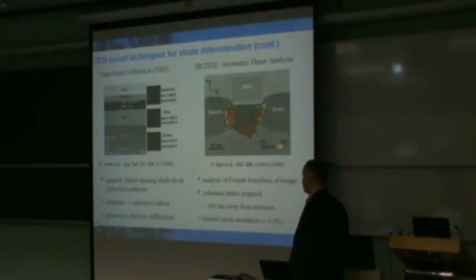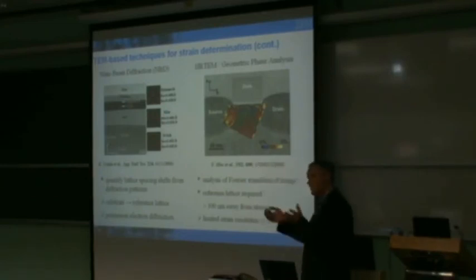So this is the analog of X-ray diffraction that I showed earlier, in which we're basically rastering the beam over a region of interest and using the silicon substrate as our reference to tell us what our unstrained values might be for the strain for the system. We then see that we're just simply measuring the change in the position of our diffraction points. And because, again, with electron diffraction, our Ewald sphere is very large,